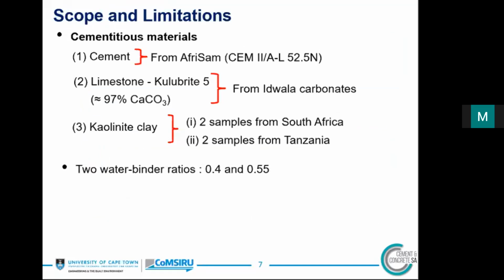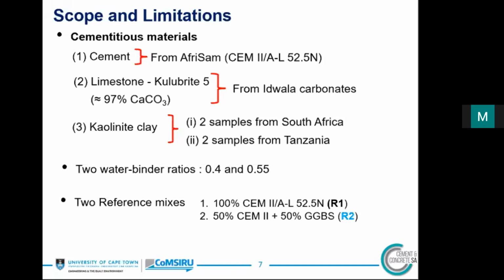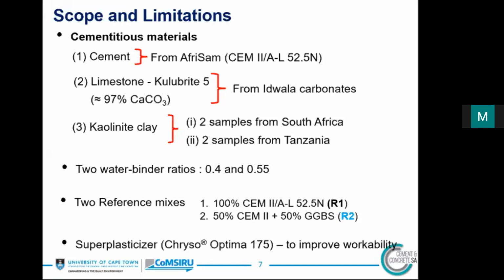Two water binder ratios were considered: 0.4 to represent relatively high performance concrete from marine environment, and 0.55 on selected mixes to represent medium quality concrete, which can be used in most common construction projects. Two reference mixes were considered. One is with 100% CEM II, abbreviated here as reference 1 or R1. And the second mix is with 50% CEM II replaced by GGBS, abbreviated here as reference 2 or R2. A superplasticizer, called the Optima 175 from Chryso, was also used to improve workability.